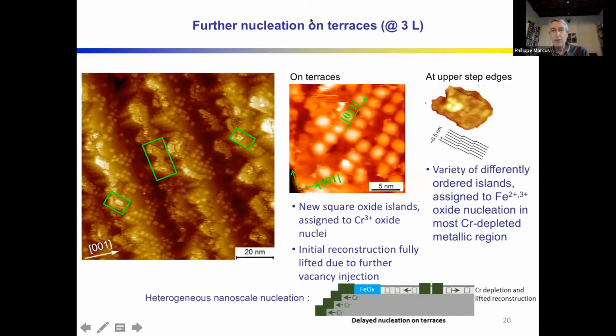Then if we continue the oxidation and look at a slightly longer exposure, then if you look at the STM image, you can see that now the terraces are also covered by oxide, which have the same structure as at the beginning. So these are chromium oxide islands, but we have other features that are near the step edge. And if we look at them in detail, they are shown here. They are consistent with the formation of iron oxide rather than chromium oxide. So this is the model here.